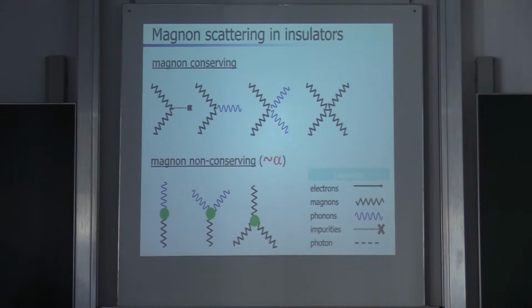Okay, so let's go to the magnon systems. We can have exactly the same story, right? You can excite your magnon system by light, or electrically as you like. So what will happen? There will be scattering processes. There are impurities which will scatter the magnons. These are elastic impurities, so the magnon energy will not change. But there's also interaction with phonons. In general, a magnon scatters into another magnon. That means that spin is conserved, but energy is not conserved. Energy can go from the magnons into the phonons or in the opposite direction. So this process will thermalize the magnons and the phonons with each other.